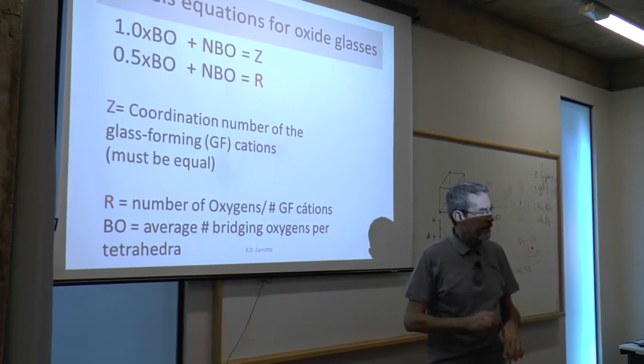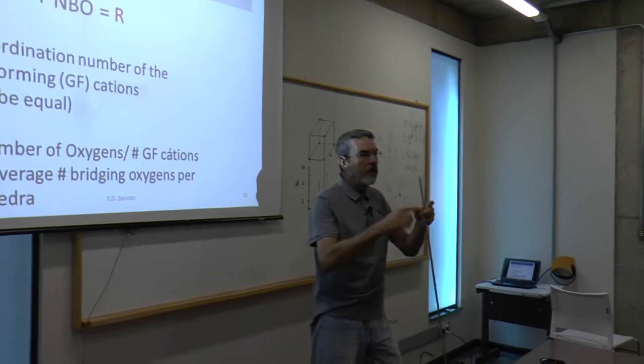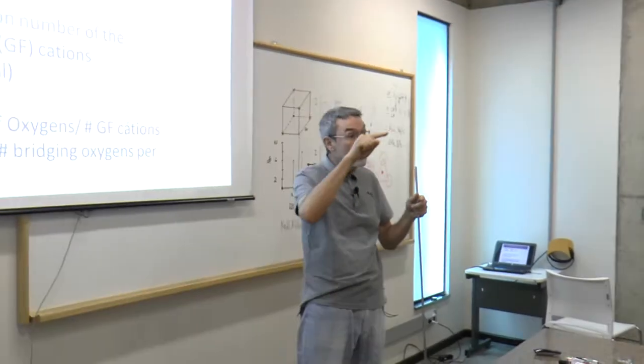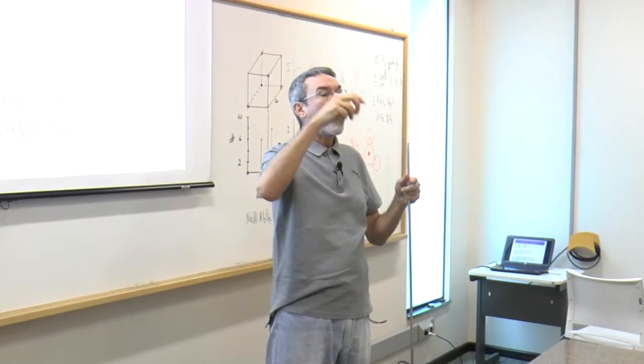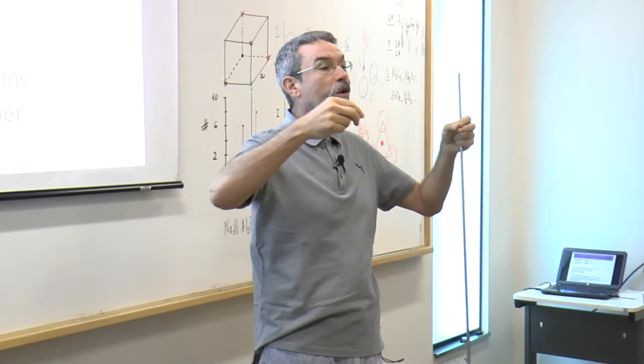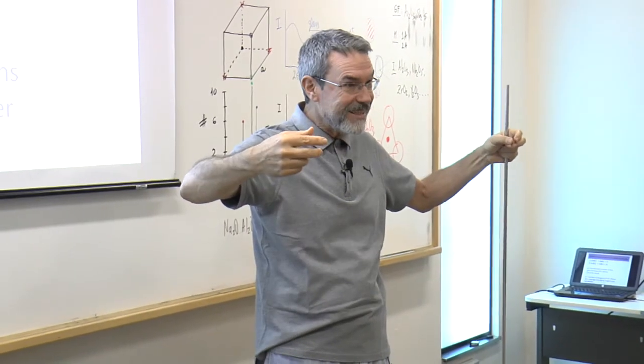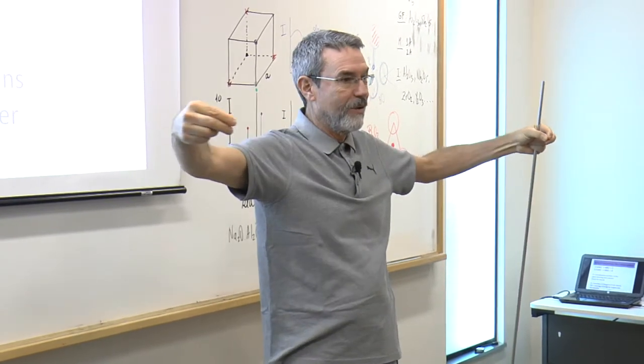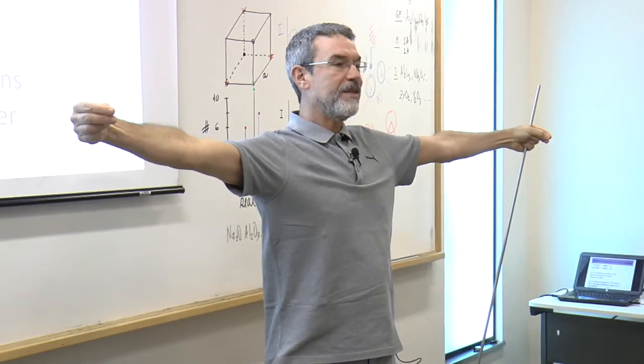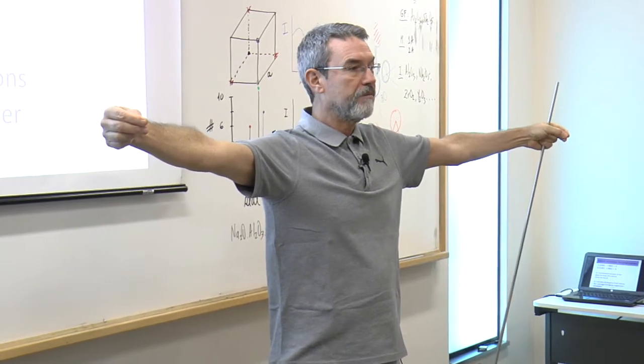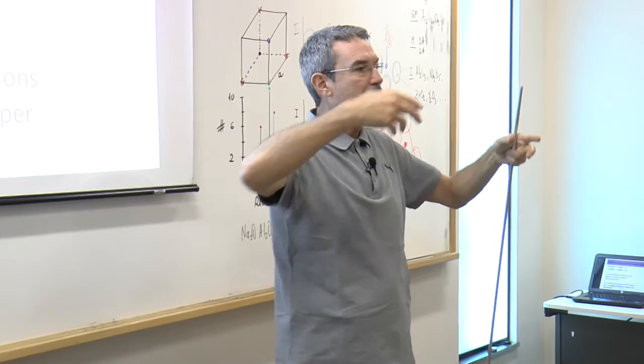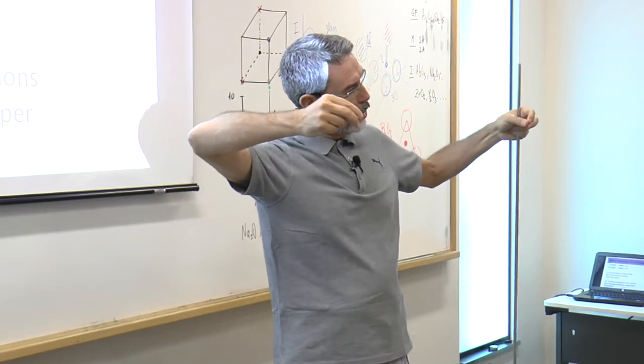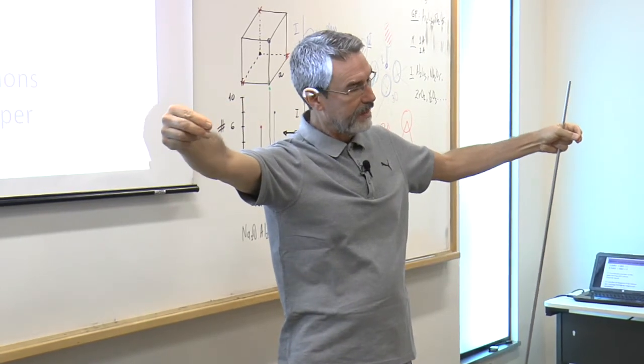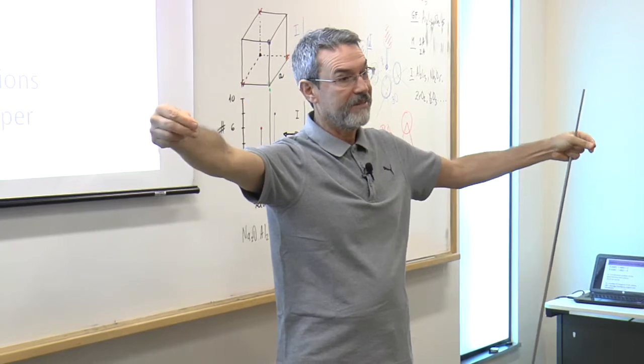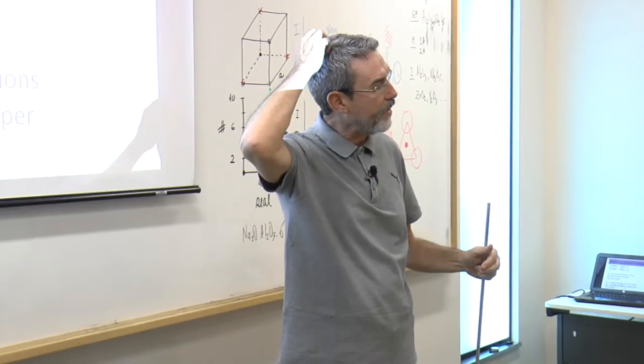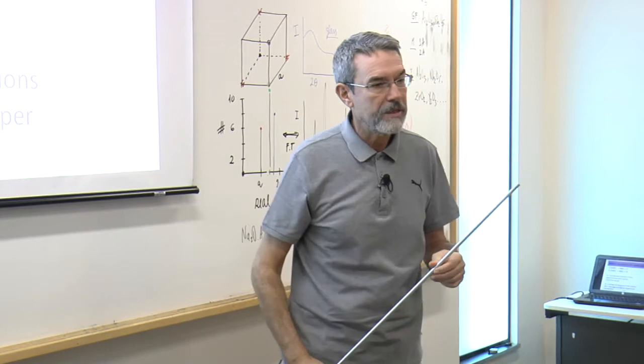That means, Graziella, that your glass has only, on average, 2 corners shared. So they form chains. This is a glass that could form long chains. If this number is 3 or more than 2, they form 3-dimensional networks, but if it's 2 or less, they form chains. This is a chain silicate. See how much information you get only by doing these calculations.